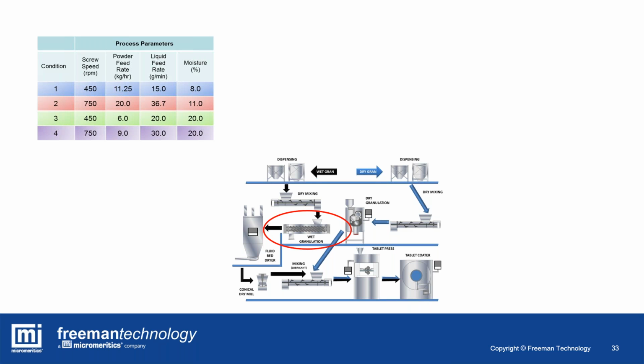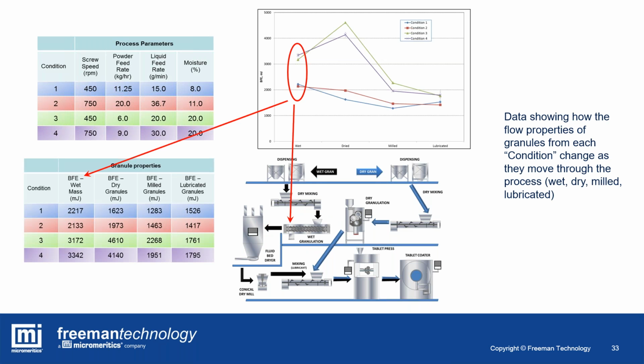In the first instance, we've got granules directly from the granulator, so they're in the wet phase, and you can see typically there's a lot of data on this screen, so I apologize. I'll try and explain the pertinent points. The lower flow energies here, around the 2000 millijoule mark, are measured from condition 1 and 2, where you have a low water content within your formulation. And then you have a substantial jump in flow energies up to 3,200, 3,300 when you go to the higher water content. So perhaps not surprisingly, if we're contrasting just water content changes, the more water you add, the bigger, stronger the granules, the higher the wet mass basic flowability energy.